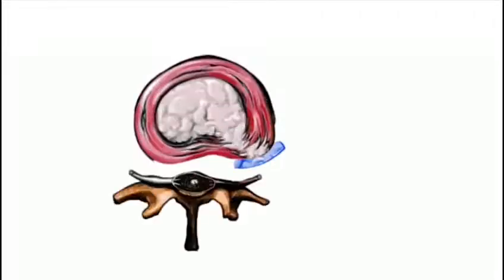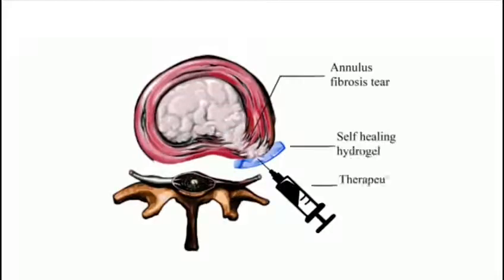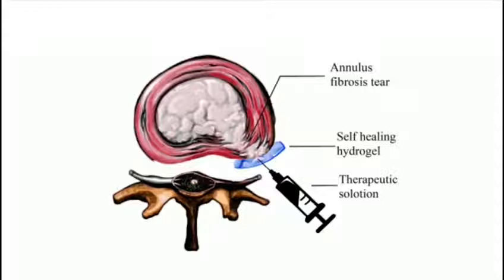Our patch is designed to cover the tear and reseal after needle puncture, preventing spillage. This will be achieved using a two-polymer hydrogel network. Some of these cross-linkers will be ionic and some will be hydrogen bonds. Hydrogen bonds can easily break and reform, therefore introducing the healing property.